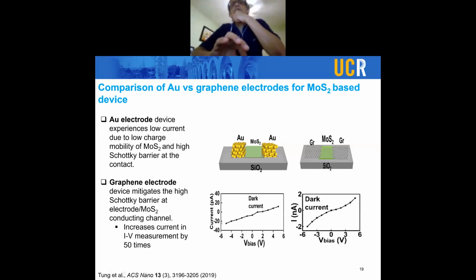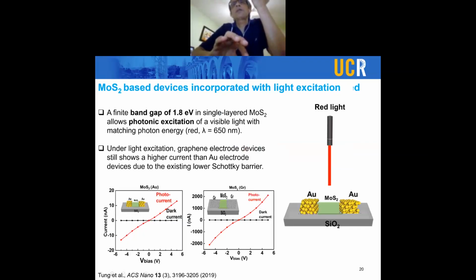here's the IV curve for this particular platform, and you can see the currents are in picoamps. When we move this into a graphene source drain electrode, you can see the currents are in nanoamps. So we have roughly a 50-fold improvement, or decrease of the resistance, when we use graphene as the source drain electrode versus the gold as the source drain electrode. So we have already a good indication that the Schottky barrier is reduced, and thereby we will get benefit.